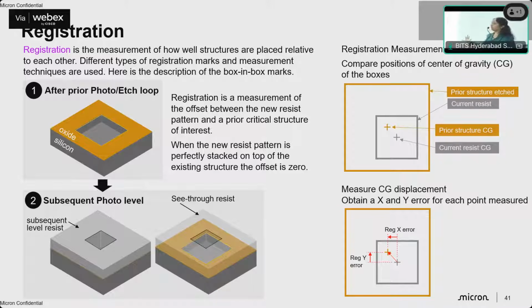If you look at the top edges of that, these two squares inside each other, you measure them at the top and then check how much shift is there. And if the shift is more than the spec limit of your process, then you will rework your wafers and try to fix it. First of all, do a root cause analysis, what caused the shift, and then fix it. This example only shows your X and Y shift, but there can be other shifts too. They can be magnification of your process. They can be a rotational component, wafer expansion, heat-level expansion. Multiple issues can happen, and you have to make sure that these lines are very well targeted, and we are pushing ourselves down to actually angstrom level of alignment here.